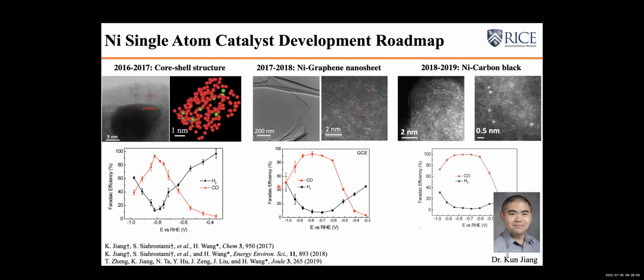The interesting part in summarizing this continuous work is that if we normalize the CO2 reduction activity on the number of active sites in all of these three versions of catalysts, they have surprisingly similar turnover frequencies. So this is a very strong side evidence to show us that while their morphology and their apparent performance are different, they all share the same active site, which is the nickel single atomic site.